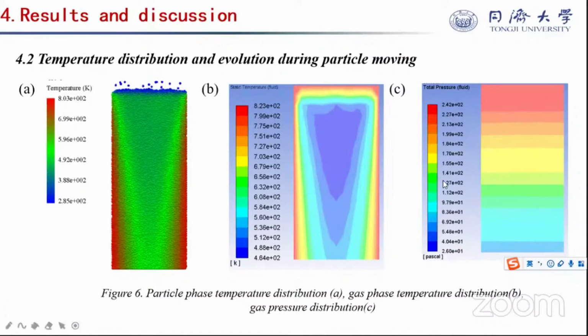The figure on the right demonstrates the pressure change from entering to exiting the reactor. The pressure drop is more than 1,000 pascal per meter, indicating that this type of reactor has relatively high resistance and should not be designed too long.